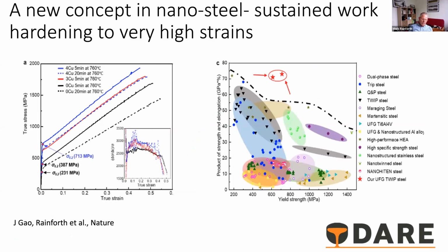So looking at the mechanical properties, we've really achieved something that was quite interesting as well as impressive, I think. The yield strength with the 4% copper alloy is typically about 700 megapascals, which is pretty respectable. It's not outstanding. But of course, the difficulty is getting both a high yield strength and good work hardening behavior so that you get a stable and large ductility.